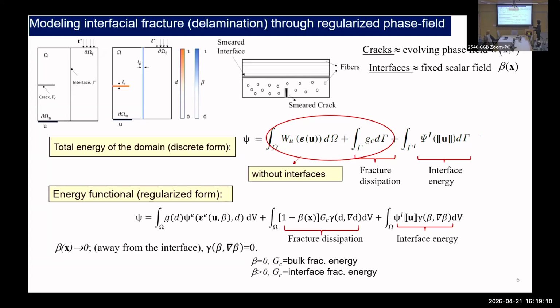So if you just think of an ideal schematic of this smoothing phenomenon, you have a sharp crack in the domain and you have a sharp interface. Both can be regularized by introducing the phase field variables d and beta and the associated length scale parameters. Okay. So with that introduction of beta and d, now my total energy in a regularized form for the domain can be written in this way. So if you just compare, these two were surface terms. Again, the fracture was ideally supposed to be a surface area term, and the interface was also a surface area term. But because we have this regularized approximation, we can craft both of these terms in the volumetric domain.